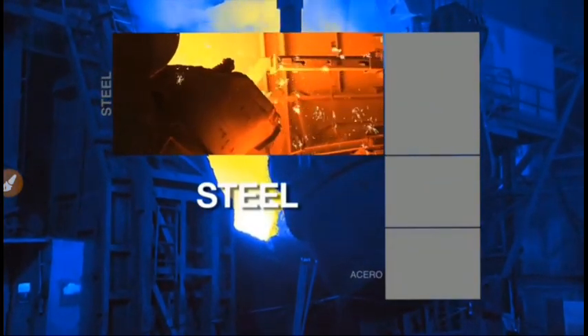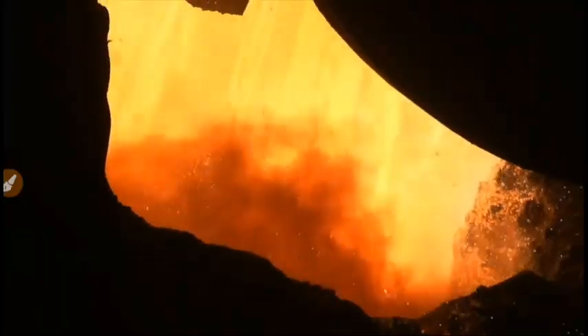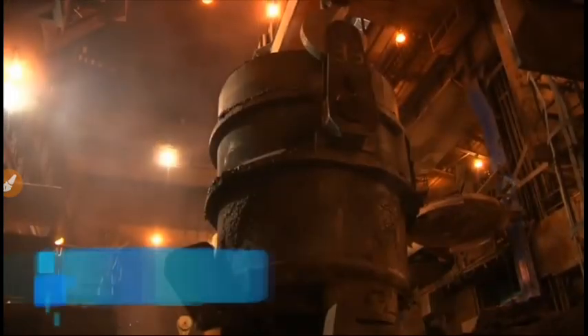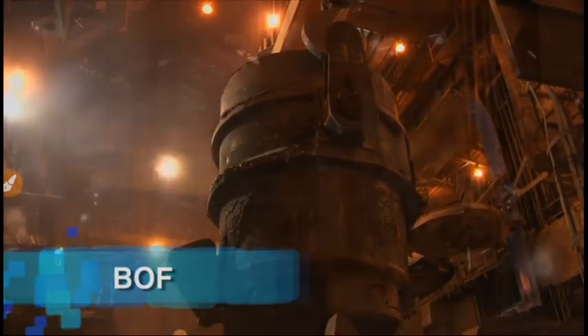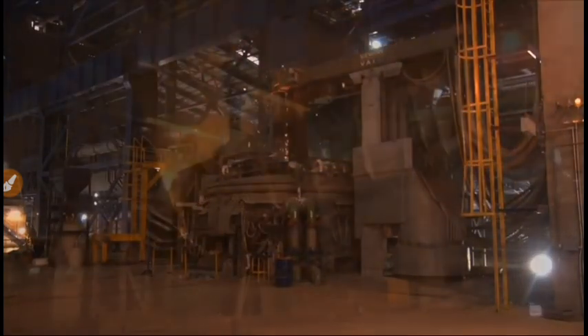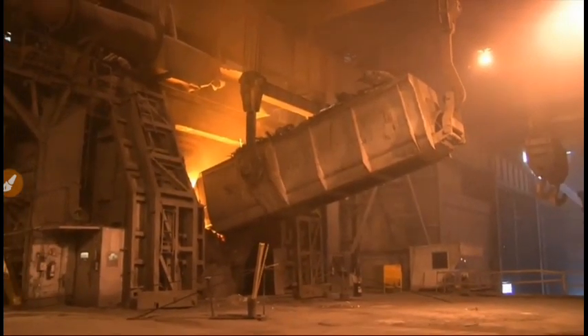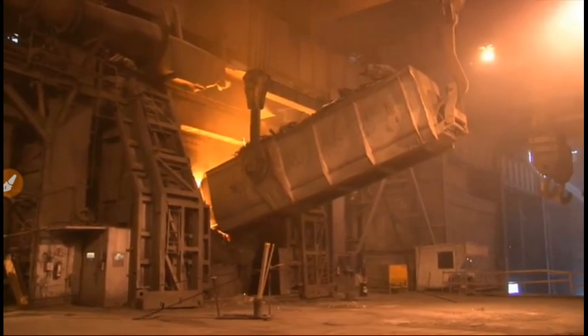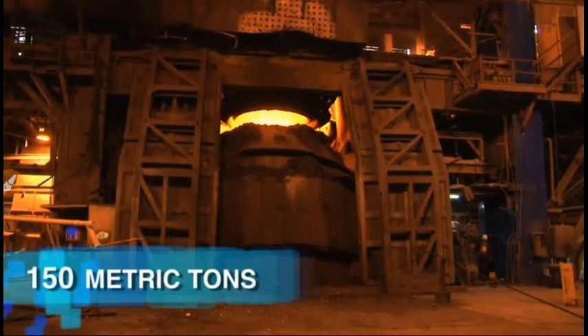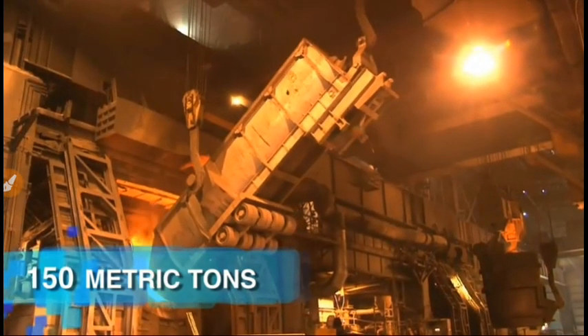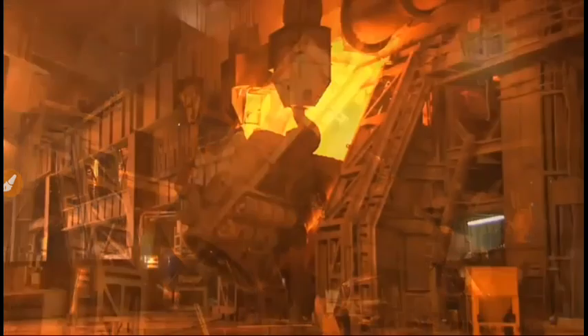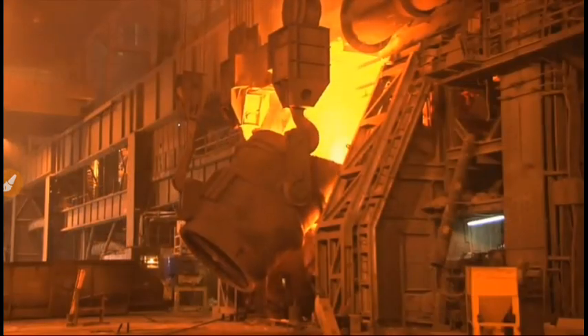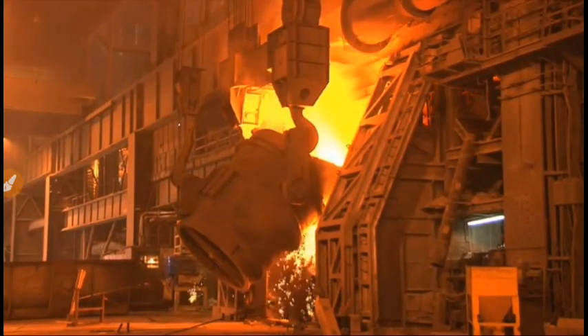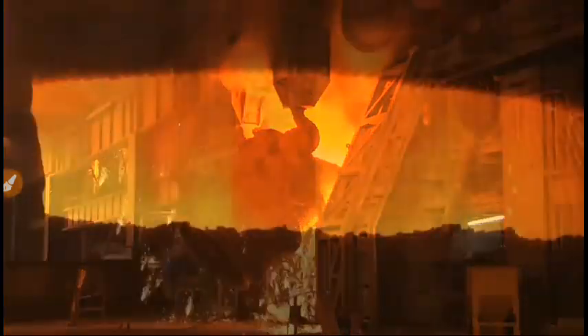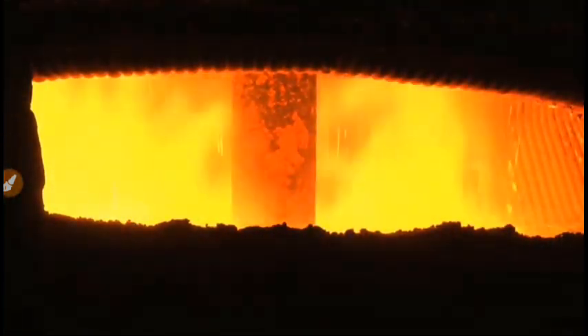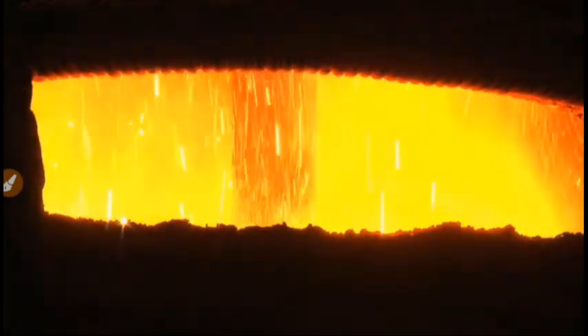For the conversion of pig iron to steel, AHMSA uses the oxygen-based technique of steelmaking called BOF, Basic Oxygen Furnace, as well as an electric arc furnace. BOF steelmaking begins by loading scrap metal into the converters, pear-shaped furnaces with capacities of up to 150 metric tons lined internally with refractory brick. When the proper amount of scrap metal has been loaded into the converter, molten pig iron is added by means of large ladles operated by traveling cranes.